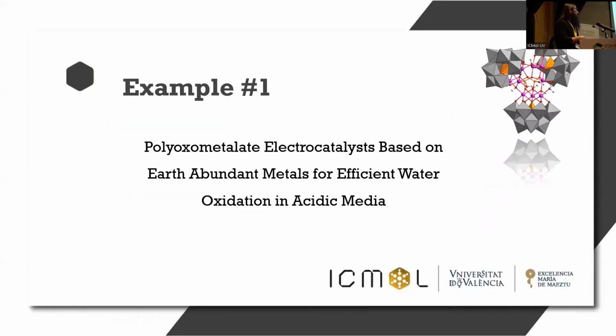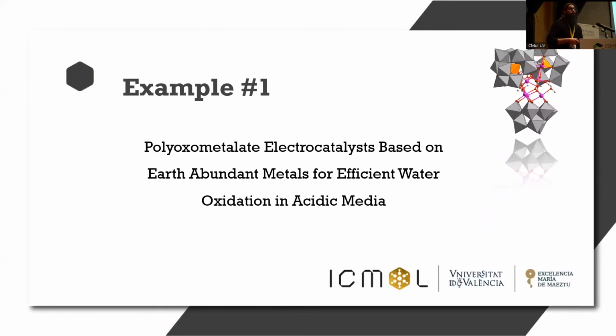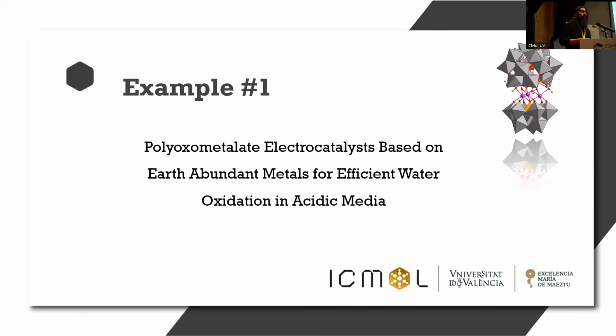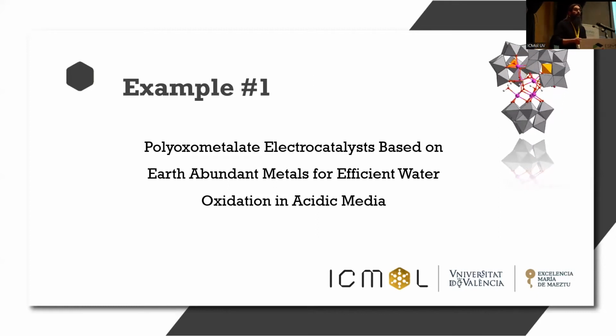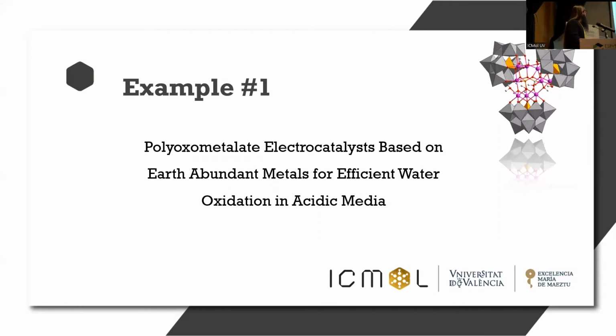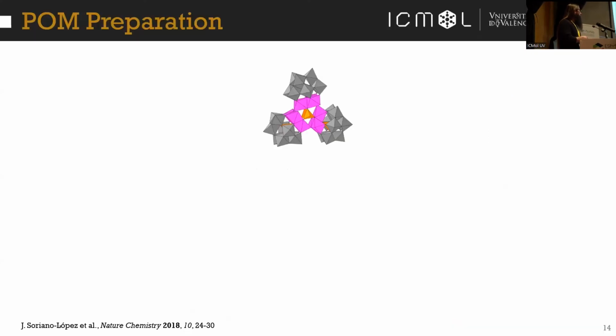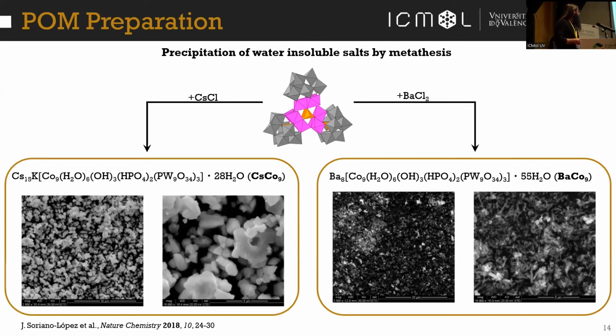In this first example, we took the cobalt-9 in the solid state, and we tested the catalytic activity under acidic conditions. For doing that, we put this in solution, and we basically obtain the insoluble salt just by metathesis. So we got either cesium or barium, and here you can see some images. The cesium salt is a bit more crystalline than the barium.